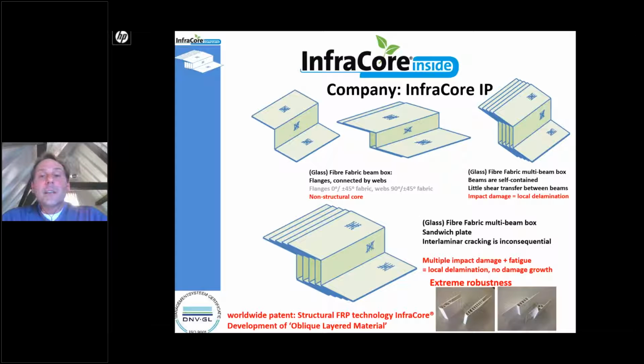What you see here is the basic technology, how the fabrics are placed. And we have solved, that's the second statement of tonight, one of the biggest challenges of the composite world, namely delamination, which means that a crack can propagate between layers, which can also happen with us. But we have made delamination inconsequential because it cannot grow further than a certain extent. And I will explain that also in a few slides.